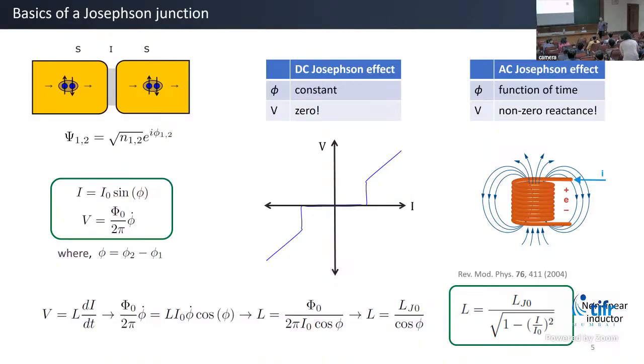One question: you said that this Josephson critical current can be tuned via the gate. Is this because the charge transfer process is Andreev reflection, not pure tunneling, and it depends on the filling of the graphene? Yeah, good question. If you have a normal barrier, like an insulator, you can't change the density of states there using gating. But in graphene, the carrier density is low to begin with, and you can add carriers by doping. So you have a normal channel, which is graphene, which you can dope electrostatically. So your junction will be gate tunable. The charge transfer mechanism in the normal insulator case is tunneling, but here it is different, it is Andreev reflection. Correct.